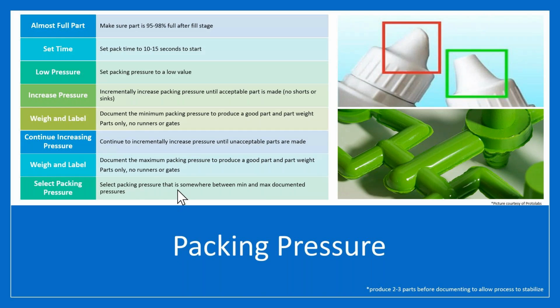and then we're going to select a packing pressure in that window. Could be 50%, could be 75%. The less pressure you use within the window, the less stress and energy you're using. So you may want to shade towards maybe 25%, the bottom quarter of the window. But regardless, you now have a window that you can pack within and produce good parts. The wider this window, the more robust the process. The narrower this window, the tighter the process.